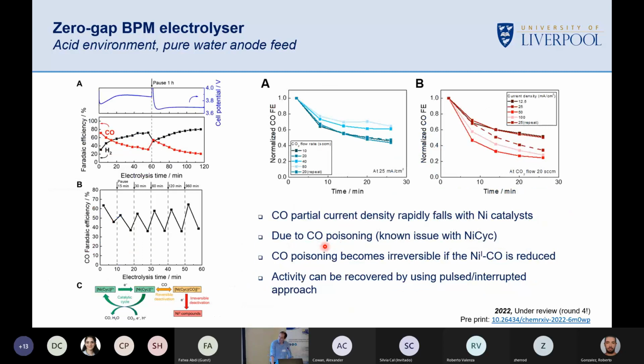Nickel cyclams are curious little catalysts. So they're present in their nickel 2 state at open circuit. We reduce them. They form nickel 1 cyclams. That's the active CO2 reduction catalyst. They go through their catalytic cycle. They produce carbon monoxide. They then have a binding constant for carbon monoxide, which is 10 times that of carbon dioxide. That's a problem, so they self-poison. If you form the nickel 1 carbon monoxide, it knocks the catalyst out temporarily.